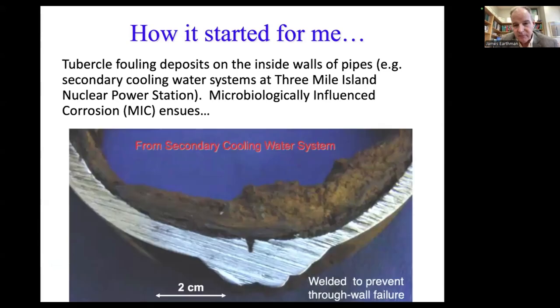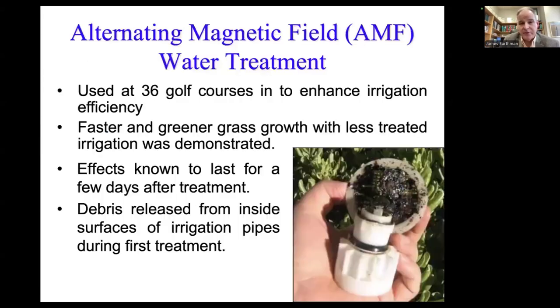Very expensive. Here's another pipe that had this problem. The localized corrosion was actually going down a weld seam for the pipe, the one weld seam that the pipe had. Bacteria are very efficient. They always colonize where they can get the fastest corrosion going, the most iron sulfide producing, and at the weld seam it's weaker there, and so that was a susceptible region for localized corrosion, and they were just going down that weld seam. And so what the operators decided to do was to weld a bead on the outside of the pipe just to extend the life of that pipe a little longer. But eventually, as you can see, they had to remove it. So this was a big problem there, and there really wasn't any way to solve the problem while we were working with them on this.